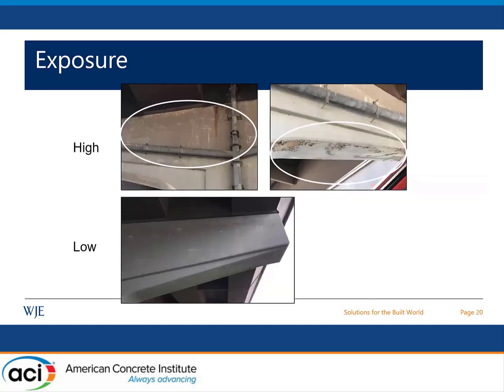So based on our field observations, we grouped the piers into two categories. One of the categories was primarily piers that were located at expansion joints, which we considered to have a high exposure to chlorides. These were typically characterized by moisture staining, corrosion staining, some efflorescence on the surface, and in some cases, peeling away of the surface coatings. Other areas which were primarily away from the expansion joints we identified as low exposures.